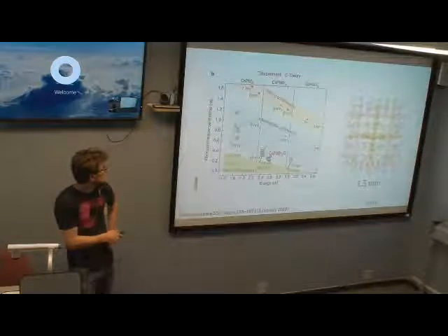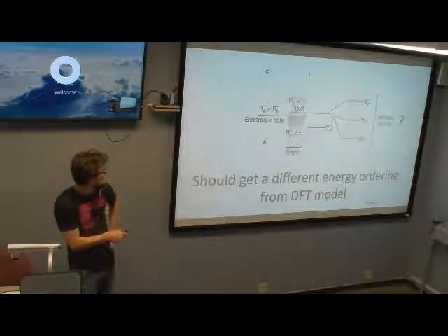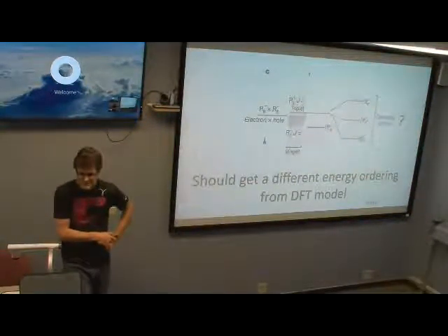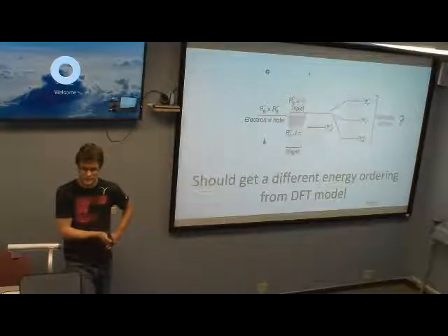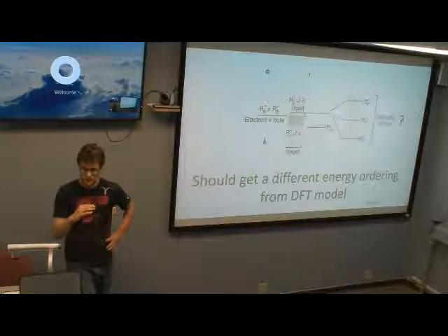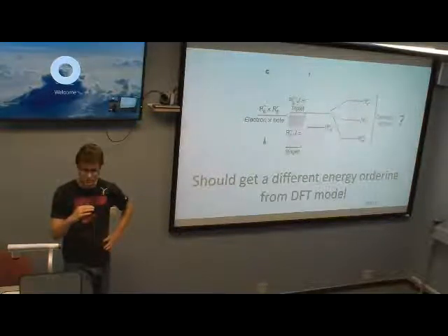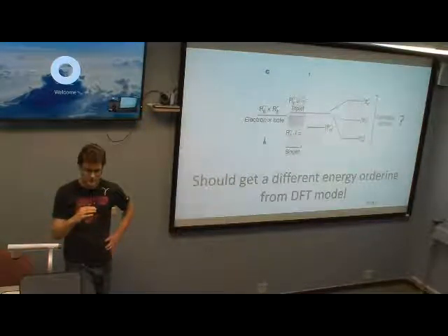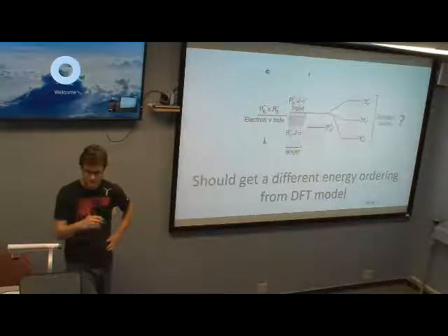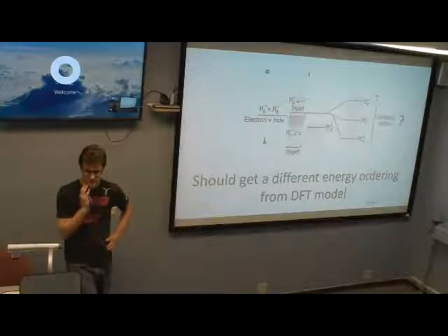But when you say low quantum yield, you expect triplets being more, less? They're more bright. In the experiments that the Efros paper did, they did low temperature photoluminescence, and they found that the radiative lifetime was like 250 picoseconds. But again, they are bright because there are three triplets, so you have 75%.